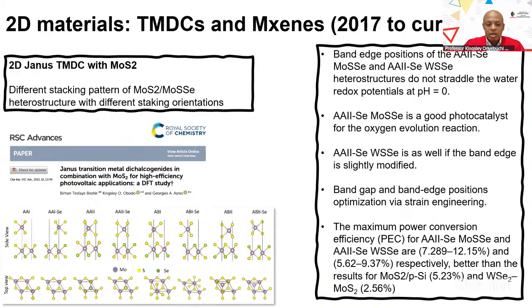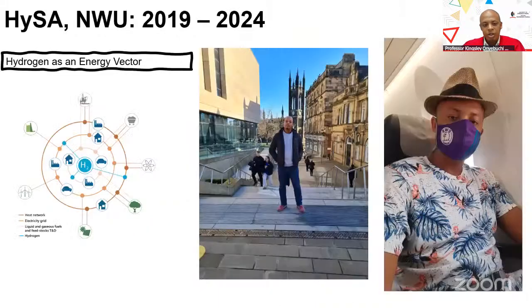We studied a lot of systems and different configurations, and this is work that is still ongoing, looking at different configurations to try and get systems that are good photocatalysts and satisfy the criteria I mentioned previously. Part of what we're still doing is band gap and band engineering, and band edge position optimization via strain engineering. We're also looking at the maximum power conversion efficiency for these systems. You can see some of them are in the range of 7.2 to 12.1. Not very good, you can see. But the idea is we can get there. We can look at a host of configurations to try and improve the power conversion efficiency.